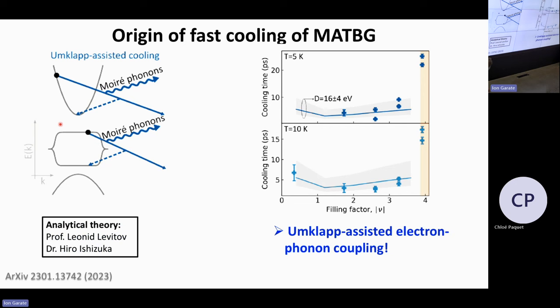And it turns out that this actually corresponds really well with analytical theory of these processes. So this is done by Professor Leonid Levitov at MIT and Hiro in Tokyo. So they have an analytical theory with not a single variable fit parameter. So what they use in that model is just the deformation potential that is known for normal single layer graphene. So, okay, the value is debated a little bit, but it's somewhere between 10 and 20 electron volt in most papers. So what we find is that if we use 16 electron volt, or even plus minus 4, so that's the variation you see here, you can actually, with a purely analytical theory of this umklapp scattering process, describe very well quantitatively the data that we observe at low temperature.